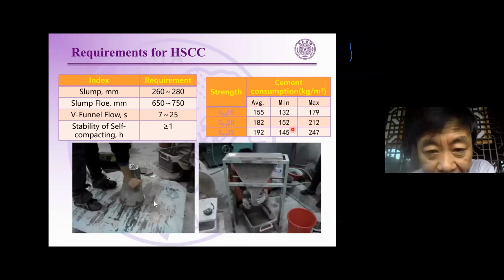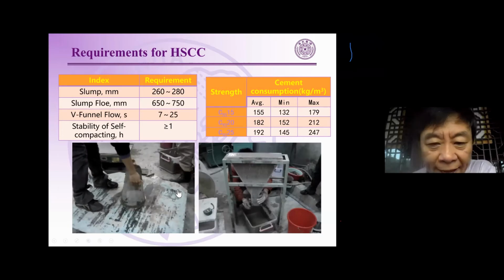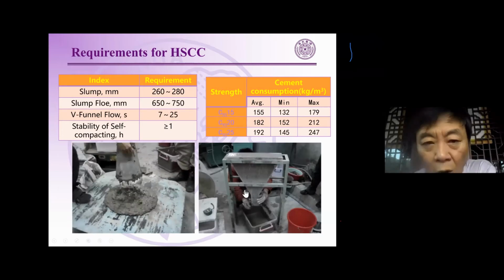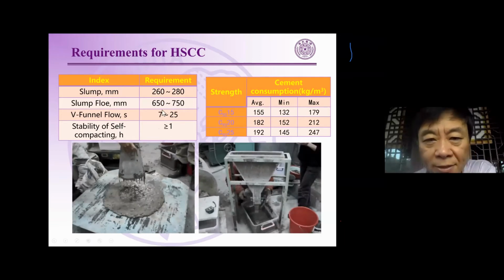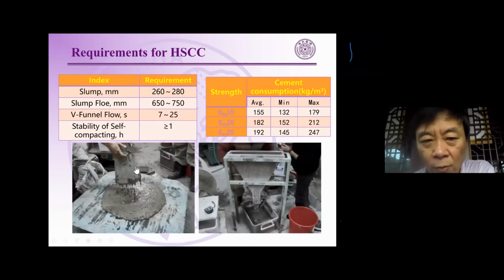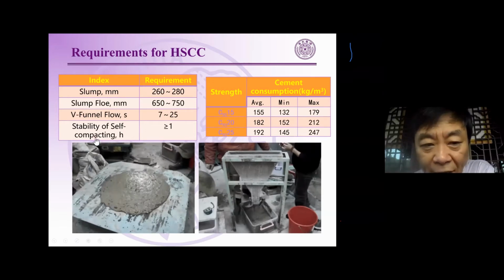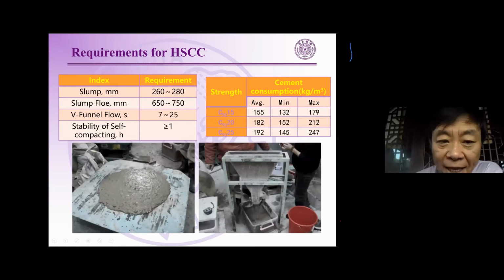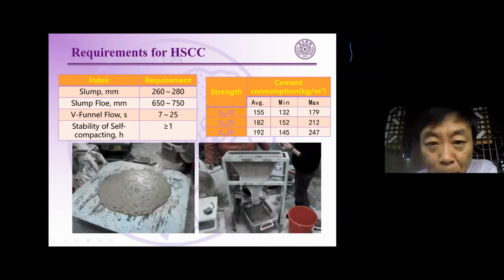And these are the requirements for the self-compacting concrete. We can say this is a slump flow test, and this is the funnel flow. We set up the index requirements for the slump flow and the funnel flow, and we also define a stability of the self-compacting concrete. That means in 1 hour, the self-compacting performance of the concrete must meet the requirements. It's not only for newly fresh concrete, you have to test it in 1 hour.